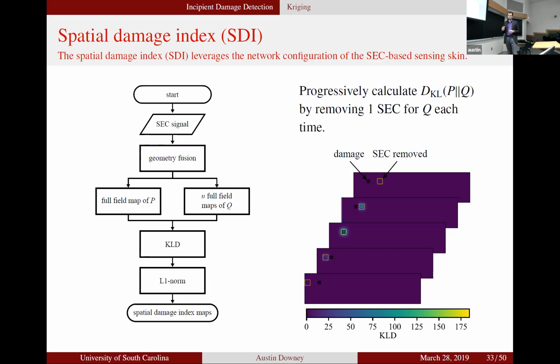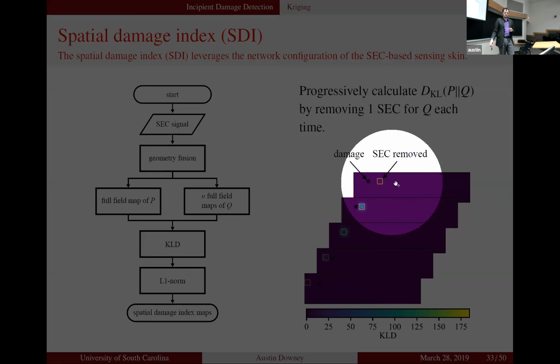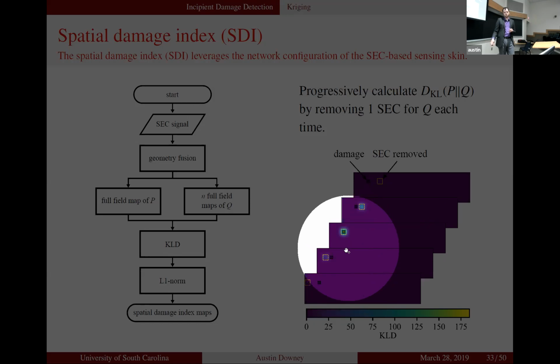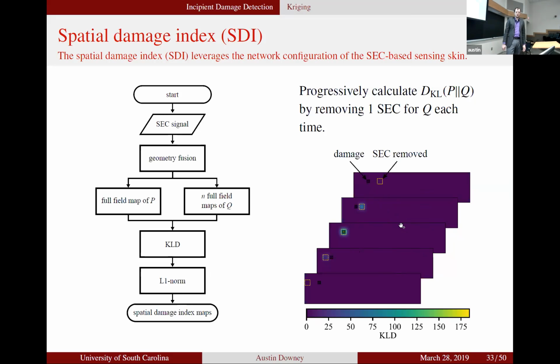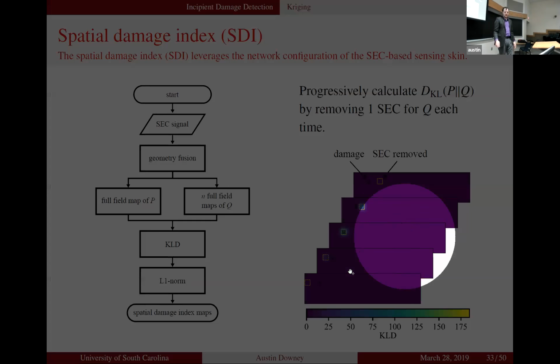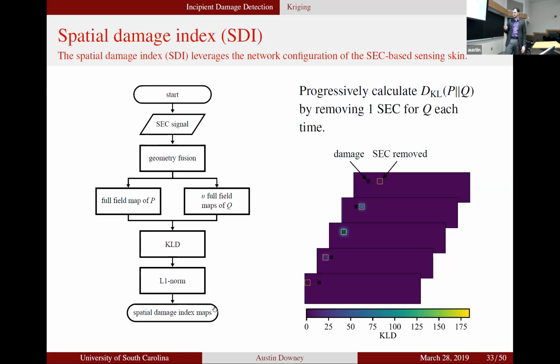And so since we have 100 sensors, we're going to get 100 maps, where each map is the spatial map with one sensor removed. We can do our Kullback-Leibler divergence between the two maps then. And so we're going to end up with 100 different maps, right, that look like this, which is the KLD between P and Q. Here we have a damage, which is this little black line. And what you can see is as we move the sensor that we remove from the data set closer to the damage, we get a very large Kullback-Leibler divergence, right? But when the sensor itself is farther away from the damage, we have a much smaller Kullback-Leibler divergence. We end up then with 100 different KLDs, and we just stack them on top of each other, take the L1 norm, and then we end up with a spatial damage index.